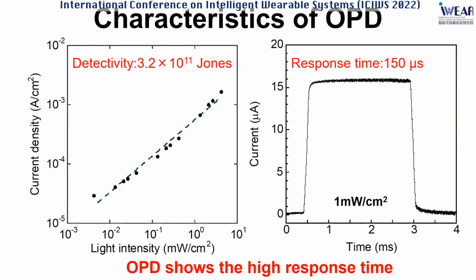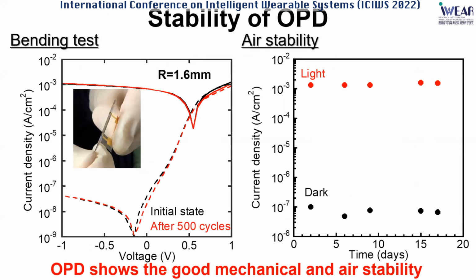And the detectivity was very good, and the response time was as fast as 150 microseconds. So such high performance OPD could be manufactured on the surface of LTPS thin film transistors. And then you may see the stability of OPD. Some people may be concerned about the air stability of organic devices, but that may be true for the organic light emitting diode. But organic photodetectors or organic photovoltaic cells have nearly solved the reliability issues, and achieved reasonable air stability in addition to mechanical stability.